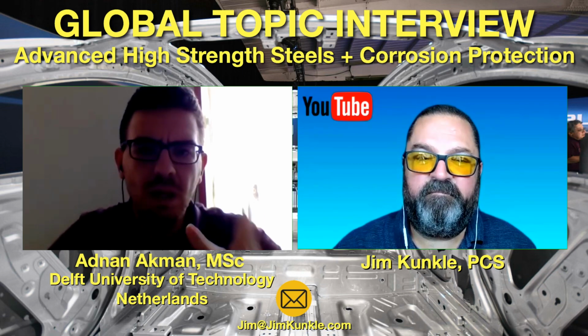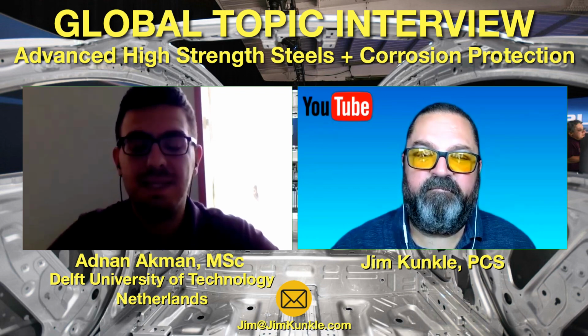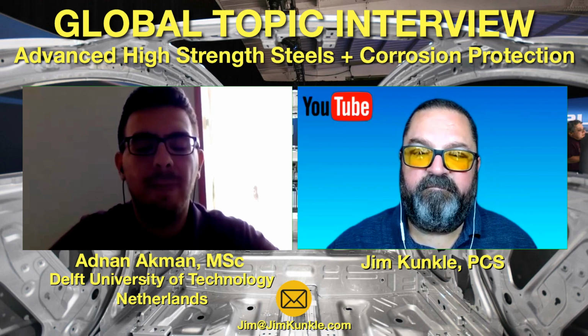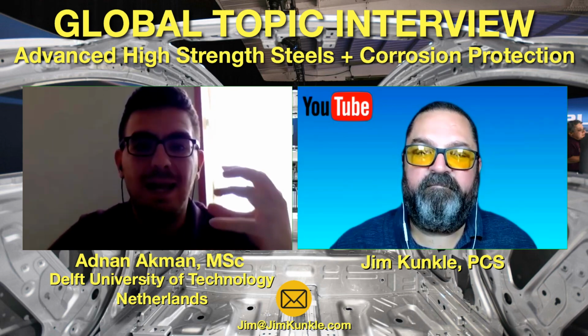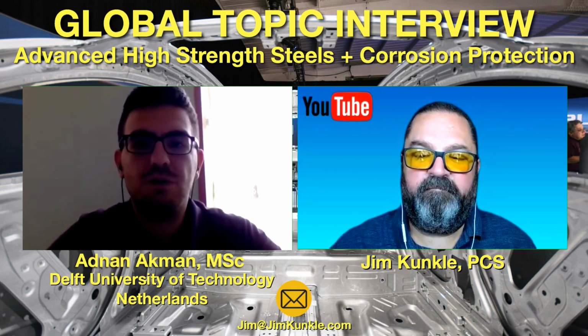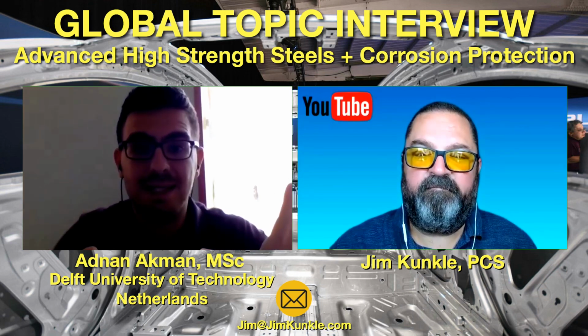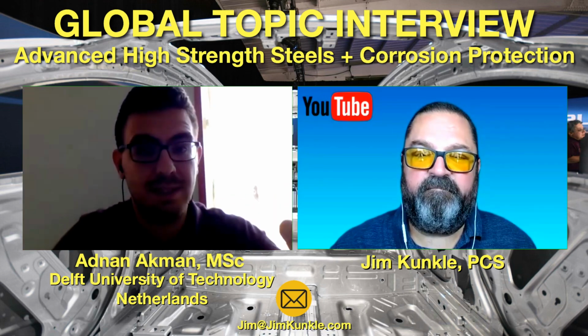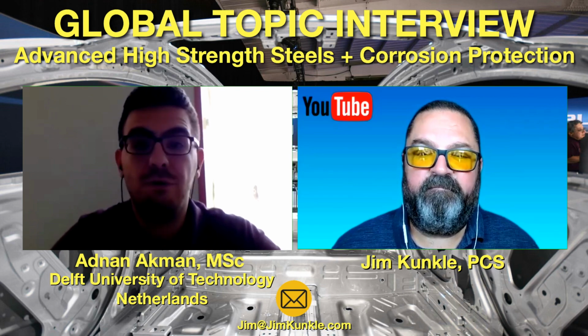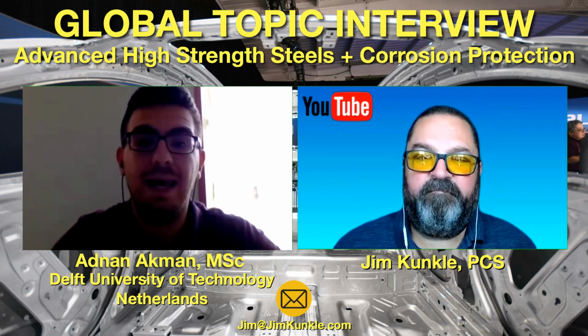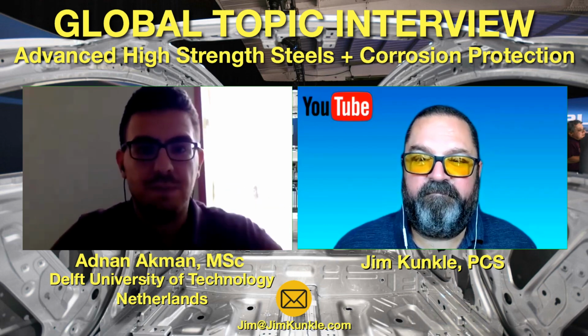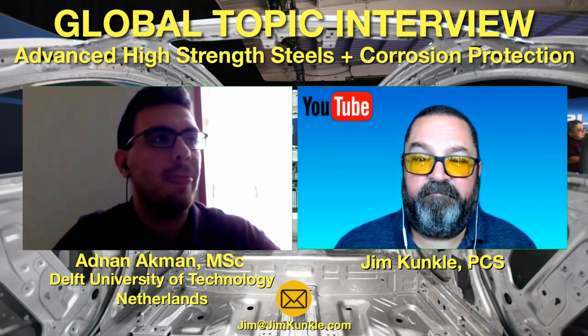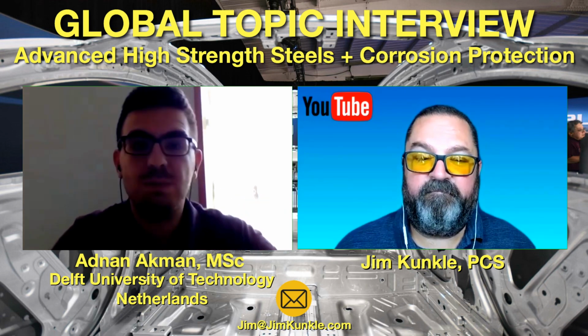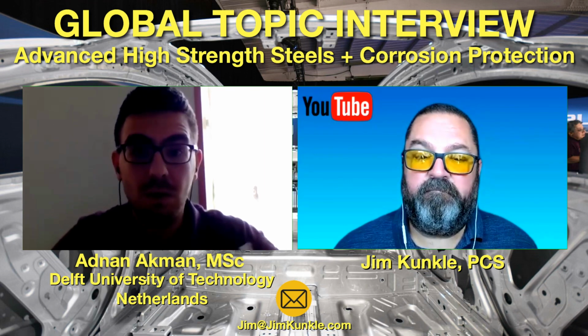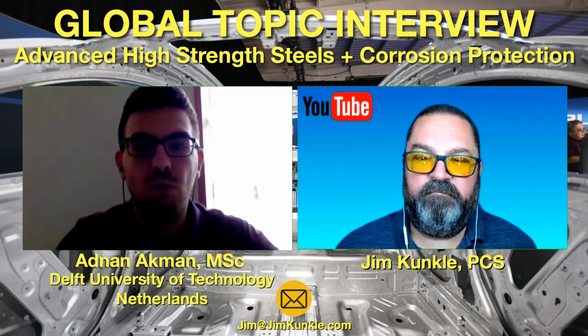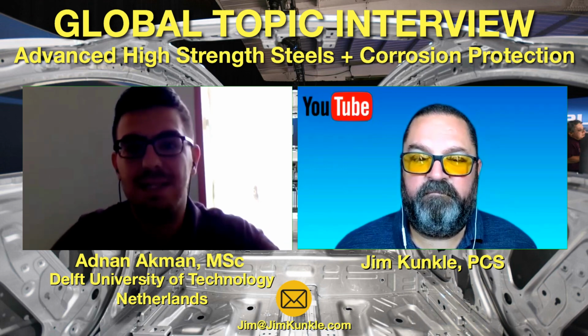In addition to dual phase steels, transformation induced plasticity steels, also called TRIP steels, are quite popular for automotive industry. As you can understand, there's a transformation. But what kind of transformation? If you check the microstructure of the TRIP steels, it is possible to see really complex microstructure, especially compared to dual phase steel. TRIP steels are quite complicated. They contain ferrite matrix with martensite, retained austenite, and bainite. So I mentioned transformation. What kind of transformation? Due to the deformation or forming, the retained austenite can transform into martensite. And with this transformation, local strength of the steel will increase. And due to this increment, work hardening rate, I mean formability of the steel, can increase easily.